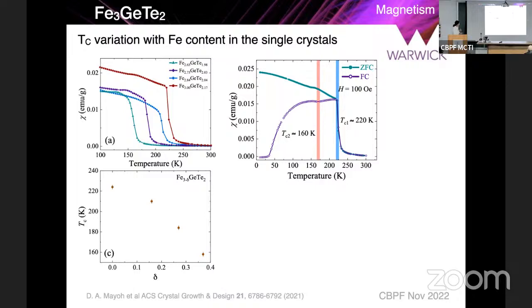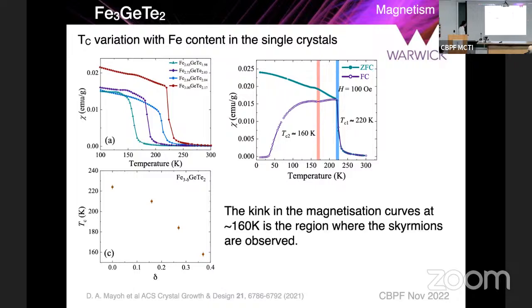You find that the TC can go up to about 230 easily, but a lot of people quote this as the TC where the transition is fully complete. So you've got to take all this with a pinch of salt. So where are the skyrmions in this material? If you plot the susceptibility as a function of temperature in these materials, you find that there is a kink in the susceptibility curve here at around 160. And this is where the skyrmion lattice is observed in these materials. So this is the region of interest that you're looking for, okay?